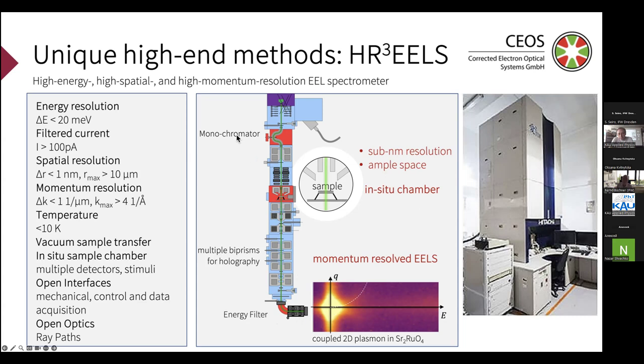And what you can do, having monochromatized electrons and having a nice energy filter here, is measure the energy loss of electrons when they pass through the sample. And this means you can do spectroscopy. You can do spectroscopy of excitons, plasmons, and all kinds of other excitations. And this you can do now spatially resolved, so with sub-nanometer resolution in principle. Maybe not for the highest energy resolution, but of course, with TEMs we have sub-nanometer spatial resolution, and you have a momentum resolution. So you can also measure the excitations as a function of Q. And that's something unique. If you combine this with the low temperature, then it's a unique method which is currently being developed here at the IFW. The first experiments are running now, first papers appear, and we are still improving the energy resolution.